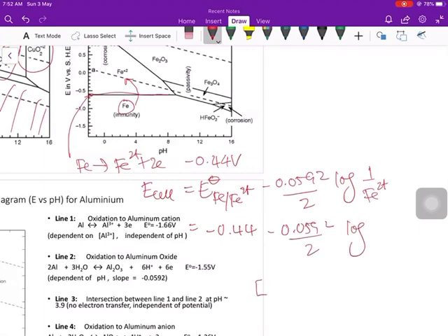In the common convention, for whatever metal, the value to put in this Nernst equation is 10 to the power of negative 6 molar. It means it starts corroding. So you will get this line. If you calculate this, you will get probably negative 0.5 something. So this is the value, between ferrum immunity and the boundary. This is the boundary.